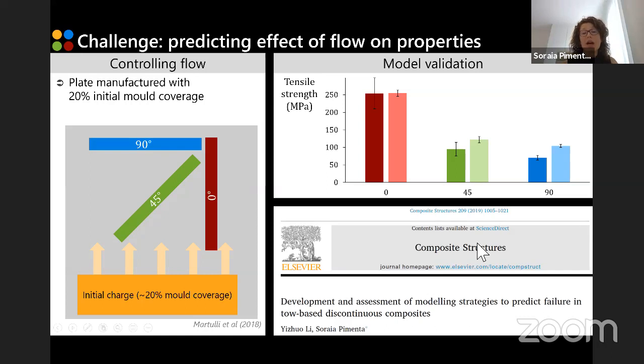So our contribution at Imperial to do this has been to develop models that, based on the results from simulations of the manufacturing process, allow you to predict exactly what properties you are going to have at each point of your structure. Now, I will not go into the details of those models, so you can check those details here if you would like. But basically, what we are able to do is to replicate the flow-affected results that we see experimentally. So the experimental results are shown in the darker color, and the modeling results are shown in the lighter color.